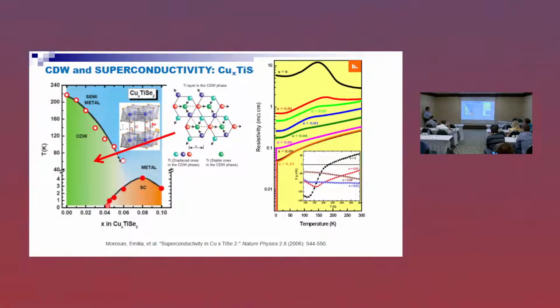Here we have the structure where I show only the titanium atoms, two-dimensional titanium atoms. The charge density wave transition is basically a shift of the atoms around one central atom towards this central atom. And we have basically this structure.